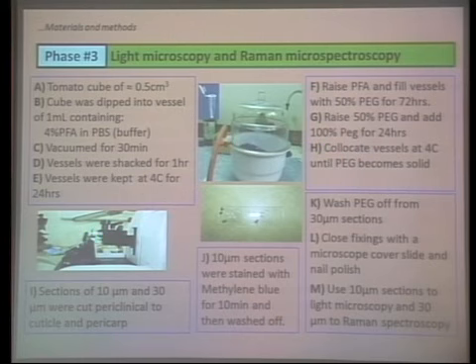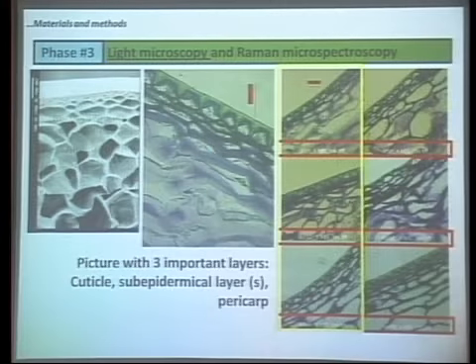of the vessels. So with this instrument here, it's a microtome. We cut sections of 10 micrometers and sections of 30 micrometers. The sections of 10 micrometers, we stain them with methylene blue, all the sections for the same time of 10 minutes. We wash it off and we cover our slices. The sections of 30 micrometers, we took them to Raman microspectroscopy, and we didn't stain them. We just washed the PEG off, and then we closed our slices.